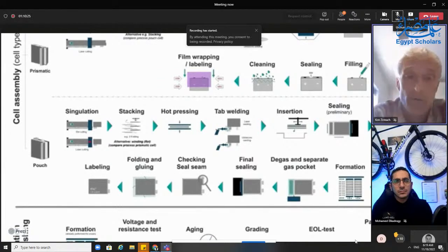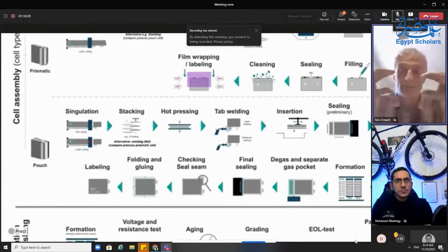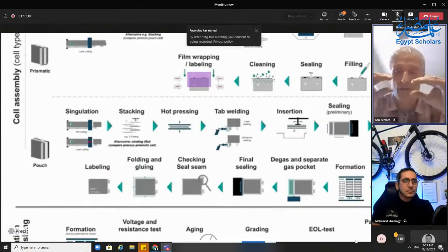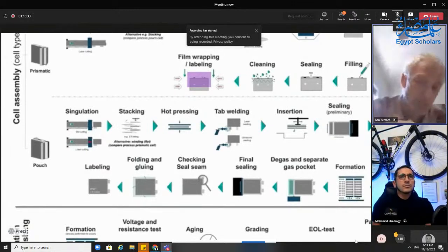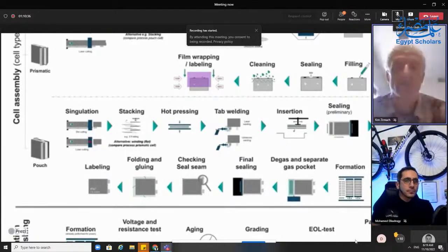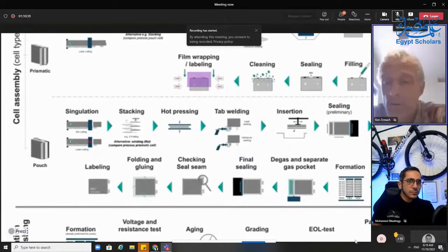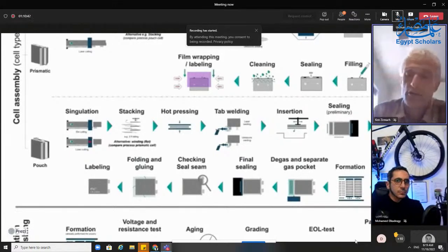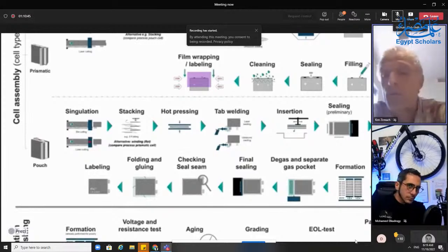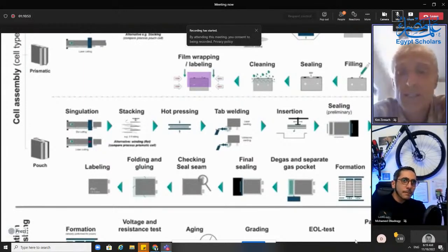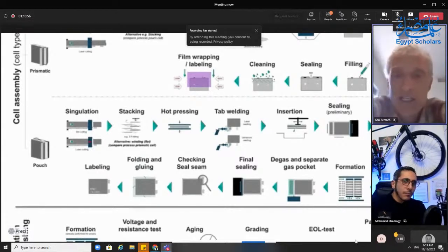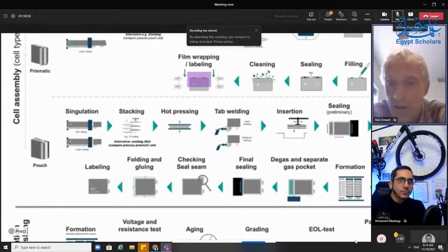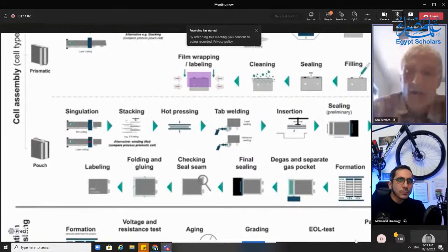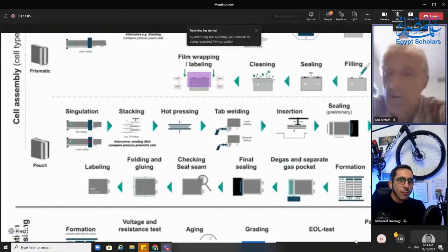So after you've made this jelly roll, sometimes you hot press it to try and get it to all stick together a little bit, but you can't use too high a temperature, and you can't use too low a temperature. It depends what separator you're using. It's very complex. Then you insert it either into a pouch for a pouch cell or into a can, usually an aluminum can. You might need to weld it to a lid first. Again, it depends on your design. And then you need to seal it. In a prismatic cell, you're usually laser welding your lid around the rim of the can. And if it's a pouch, you're doing a heat seal.